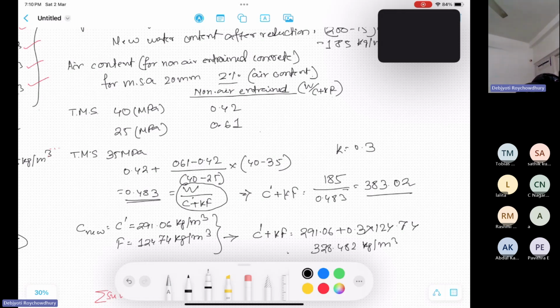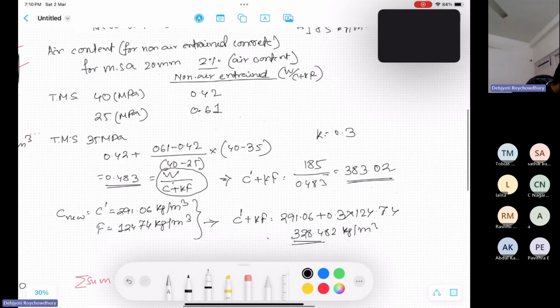However, based on the chart we are getting 383, while with the formula we are getting this other value. So you have to be careful about this methodology, because the result can differ based on the methodology. Otherwise, you can simply follow our first calculations, where you can easily find out the fly ash content and all these things.